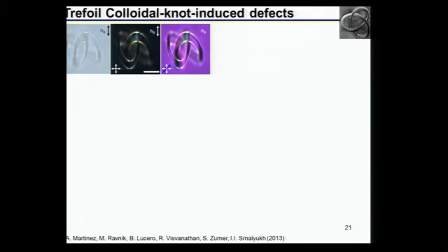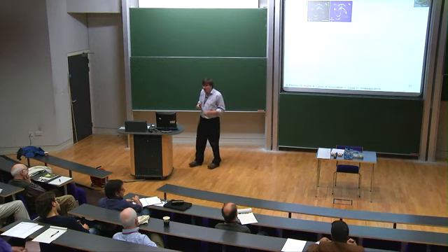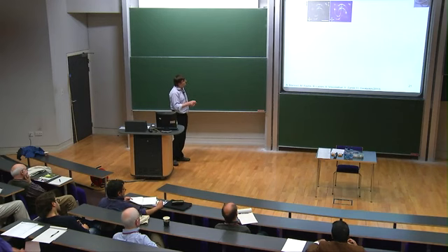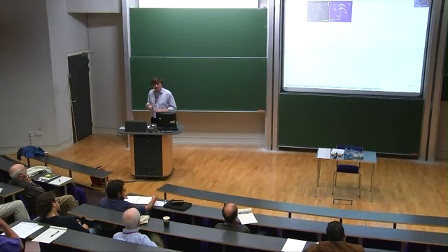And what that means is those are really colloidal particles that now can be probed as we introduce them into a liquid crystal medium. So here you can see a trefoil colloidal knot with tangential surface boundary conditions as it's introduced into a liquid crystal medium with well-defined far-field liquid crystal director. And so you can observe already point defects on the surface of this particle because this particle has tangential boundary